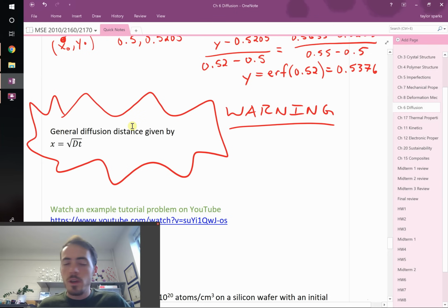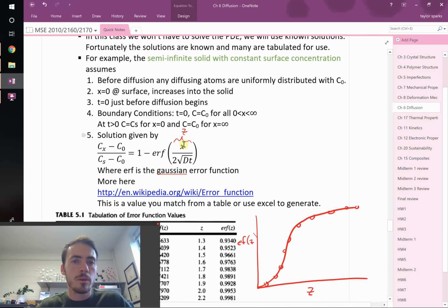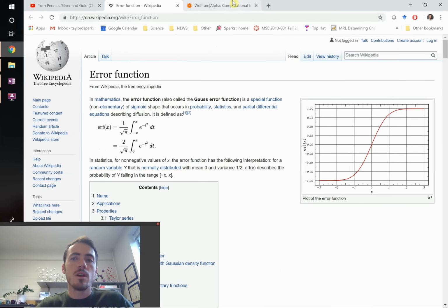When you heat something up and you know what the species is that's diffusing, and what it's diffusing into, then you could get an approximate diffusion distance under the conditions if you know them, right? Here's what the approximate diffusion distance is. It's equal to the square root of the diffusion coefficient times time, okay? Now, if you look at that, what we've really done is we've said x is equal to root Dt. If we go back up here and plug in root Dt for x, then your error function just becomes the error function of, the root Dt's cancel, just 1 over 2. So the error function of 1/2. What we're really saying is, what's the concentration?